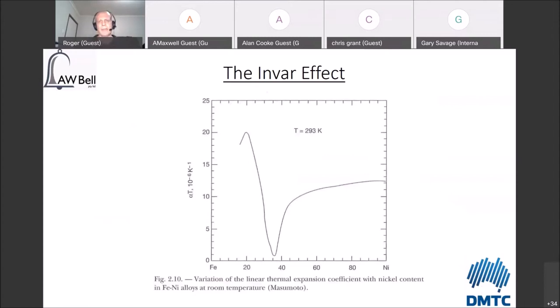Basically, on either side of 36% nickel you have what tends towards a normal coefficient of thermal expansion, but right on this particular concentration, and a little bit either side of it, you tend to get a very, very low coefficient of thermal expansion. So this is what's more commonly termed the Invar effect, and some materials display it, but nowhere near as significantly as the iron 36% nickel material.